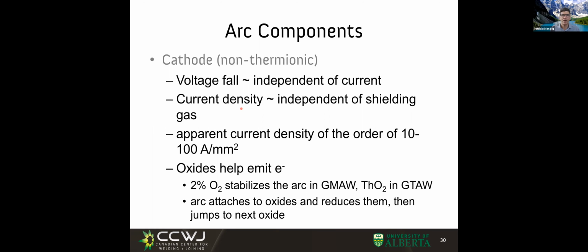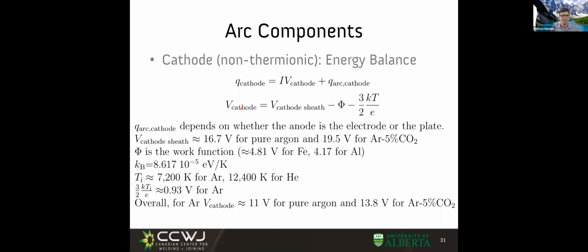And this is why when we are doing TIG welding of aluminum, we use variable polarity for cleaning the plate. We discussed that. But when we change the polarity and the electrode is positive in TIG welding of aluminum, the plate is negative and the plate is a cathode. And the arc attaches to the oxides on the aluminum and cleans it up, right? And these are the mini lightnings that we don't see.